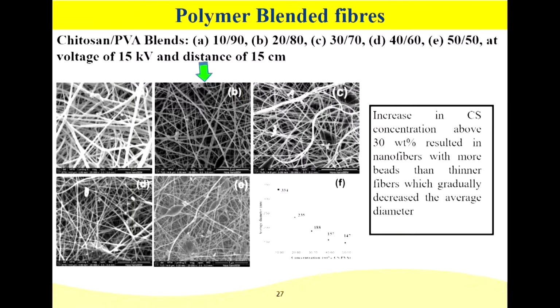But we also looked at the chitosan PVA blend. Instead of working with just one polymer, we blended the two polymers with different ratios, and you can see that these affect the formation of the fibers. Chitosan has a problem of solubility, and also charging, even though it's highly biocompatible, and it has very important properties that can be used in biological fields. So as you increase the amount of chitosan, you end up with fewer fibers and start to form some beads. And you don't want beads if you are really trying to make fibers. The challenge when making fibers is to eliminate as many beads as possible.